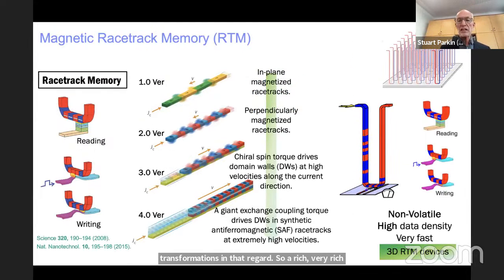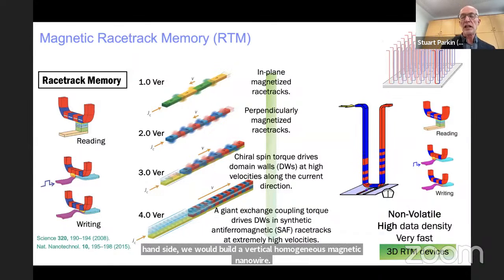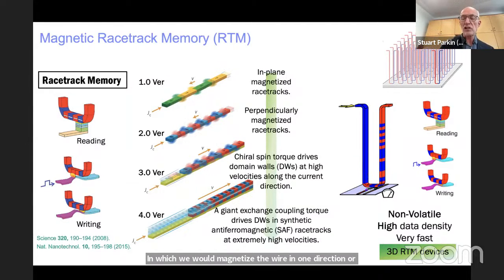So now why are we interested in these objects? We're interested mostly because we want to build a magnetic racetrack memory. And let me just remind you what that is. I've been working on this now for more than 20 years, since I first proposed this concept in 2002. It's a long time ago. And the concept was, as shown on the right-hand side, we would build a vertical homogeneous magnetic nanowire in which we would magnetize the wire in one direction or another direction, in these blue and red directions, and we would encode digital information as the domain walls, the walls between the blue and red regions, which I said at the beginning can be nanoscopic if you design the material properly. And the idea is that the presence or absence of this domain wall would be a 0 or a 1.